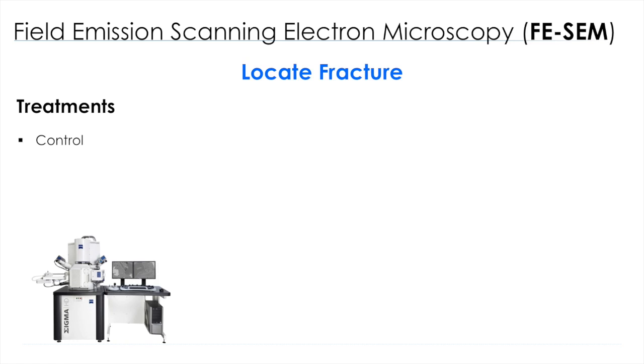The third and last technique to locate fractures, we used field emission FE-SEM, and we had 3 treatments in this part of the study: control, water soaking during 72 hours, and the last treatment, which exposed OSB to the same cycle of wetting and drying as I mentioned before for the macrophotography.